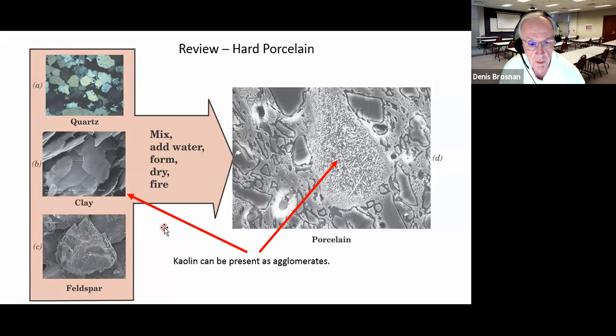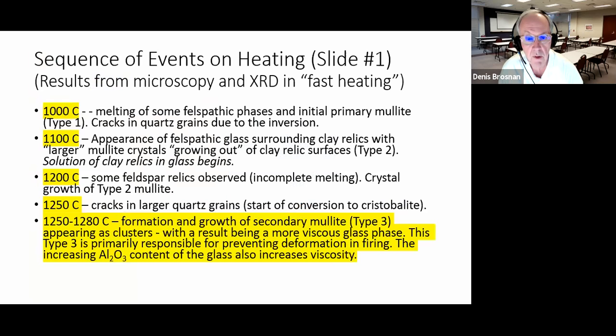Recall that when we talked about earthenware ceramics, the amount of vitreous phase was maybe as high as 6% or thereabouts. But now we have a very large amount of vitreous phase, and we see residual silica particles in this microstructure. We see a continuum of glass with little black pores in it. And this may be a clay relic showing mullite crystal development on the surface. So that was hard porcelain. There are many types of porcelain, and we didn't certainly try to cover them all. One important slide was the sequence of events on heating.